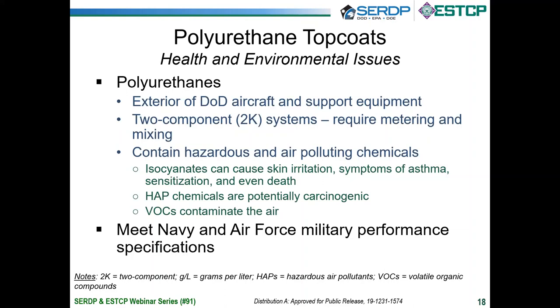Okay, so a brief overview about polyurethanes. For those who may be new to this area, polyurethane top coats are found on the exterior of DoD aircraft and ground support equipment, and this is for the Navy, the Marine Corps, and the Air Force. These polyurethane materials are two-component systems, meaning that they're composed of one component, which contains hydroxyl functional chemicals, and a second component, which contains isocyanate functional chemicals. These two components are then mixed together in a very specific ratio, which, as I state here on the slide, they have to be metered at a very specific ratio in order to obtain the preferred performance